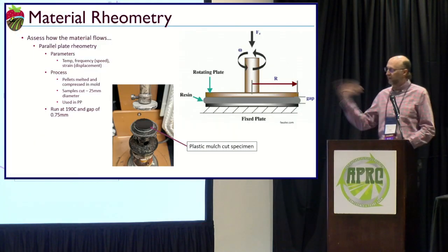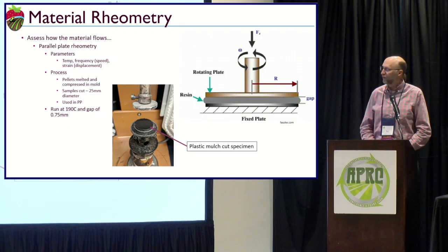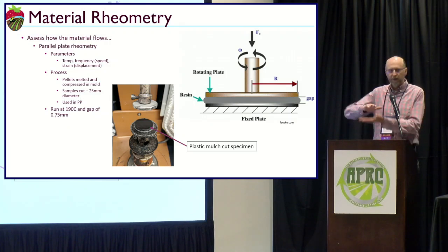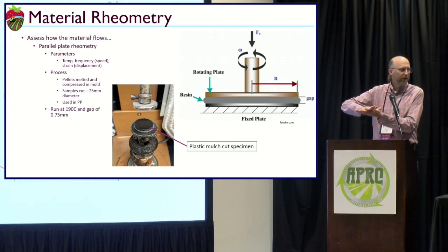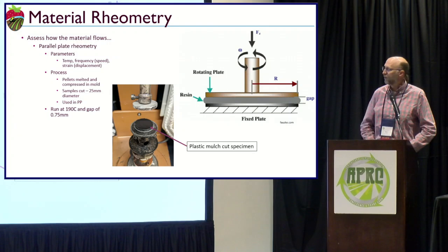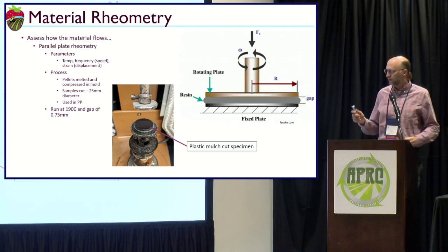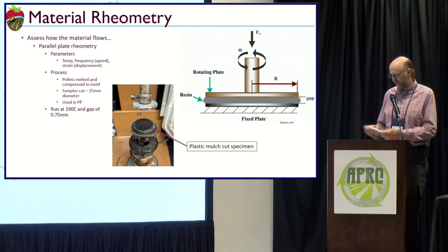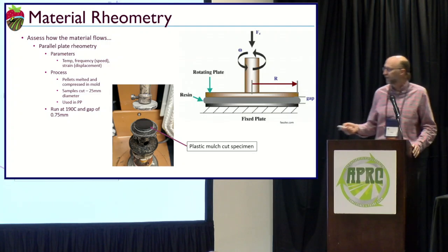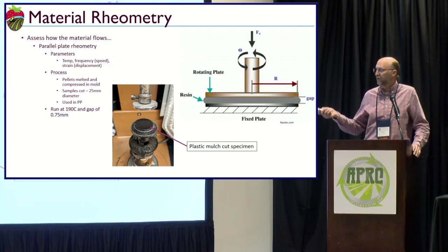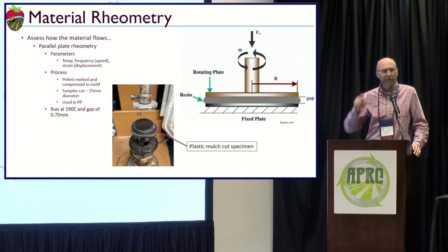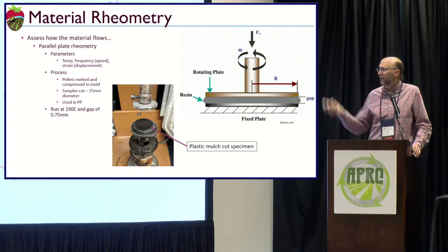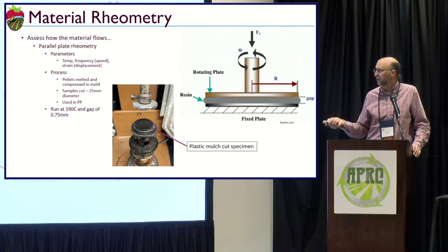We basically cut our samples out, and what you do is heat it up, and then spin that plate and measure the load it takes to spin it. We're using it at 190 degrees C, so everything should be pretty melted. We made our material out of the as-is material, so it has a bunch of the contaminants and soil in there. We had a gap of about 0.75 millimeters.